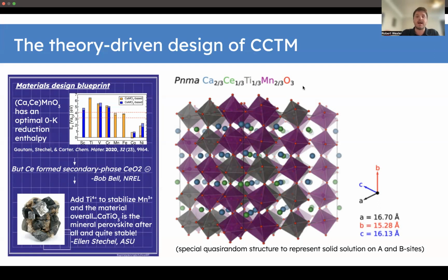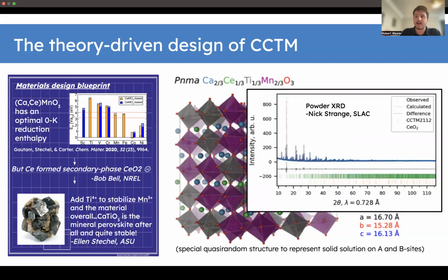calcium, cerium, titanium, manganese oxide, with 2/3 calcium and 1/3 cerium on the A site, and 1/3 titanium and 2/3 manganese on the B site, in a Pnma crystal structure, which is the crystal structure of calcium titanate. Here's a special quasi-random structure used to represent the solid solution. And that was simulated, but then it was made by Bell and Ginley at NREL, and powder XRD was done by Nick Strange at SLAC, and it was shown that the observed crystal structure of CCTM in a very similar composition almost nearly matched CCTM predicted by theory.